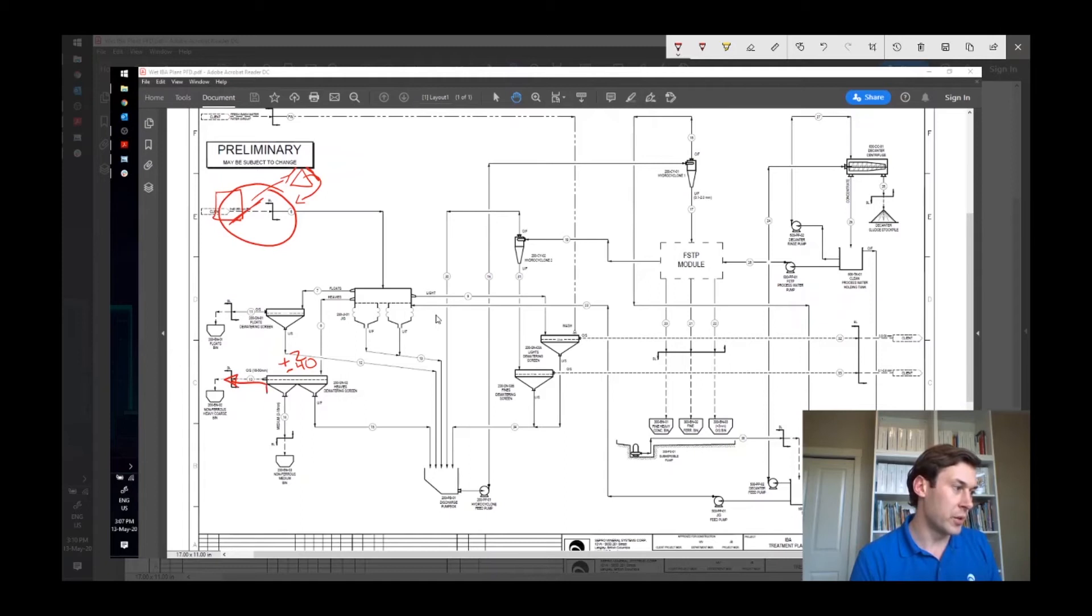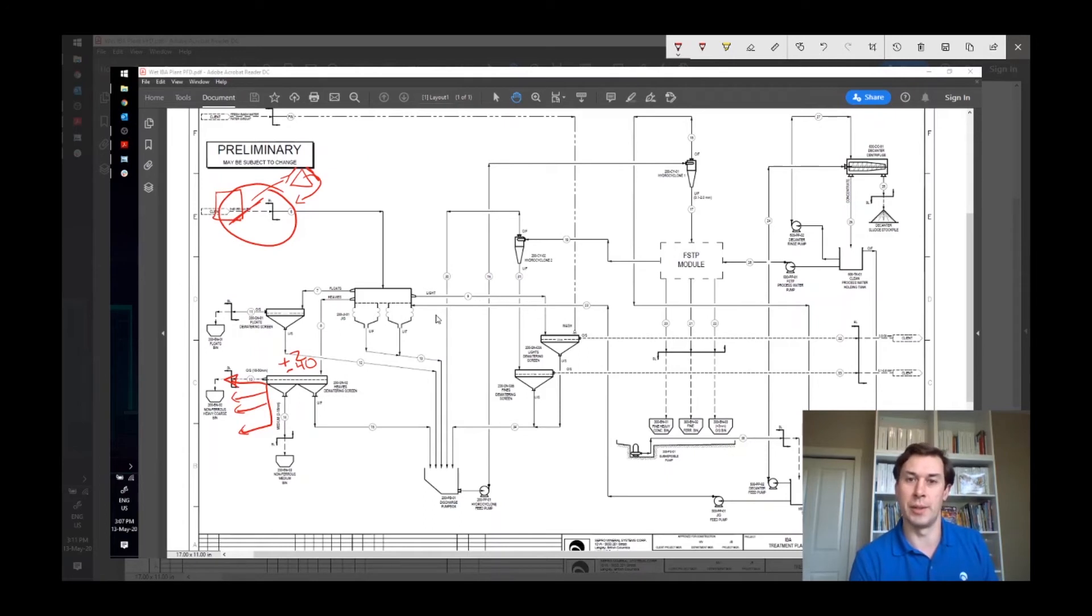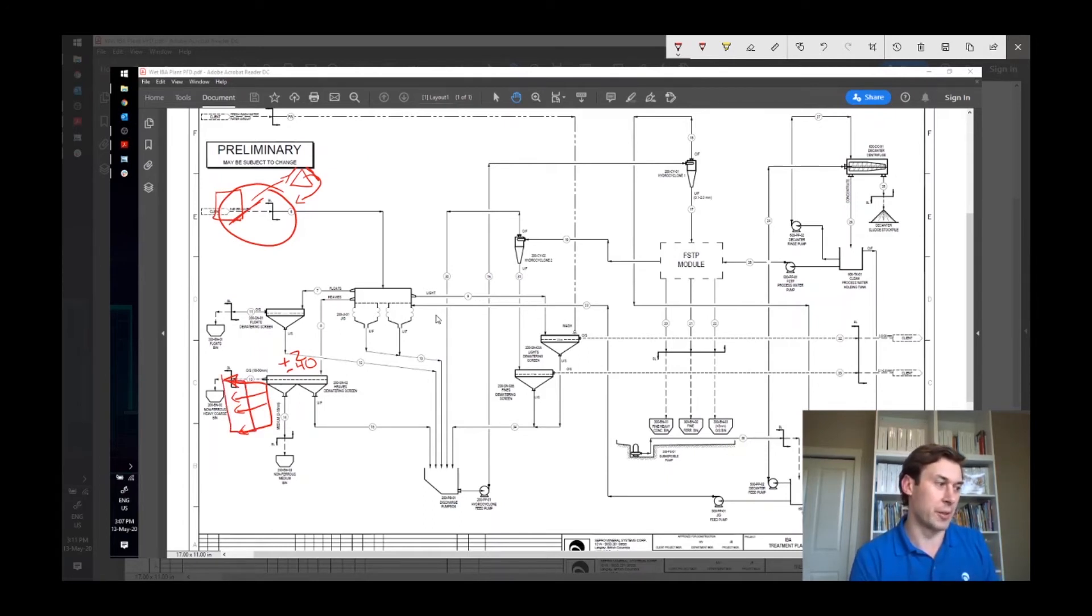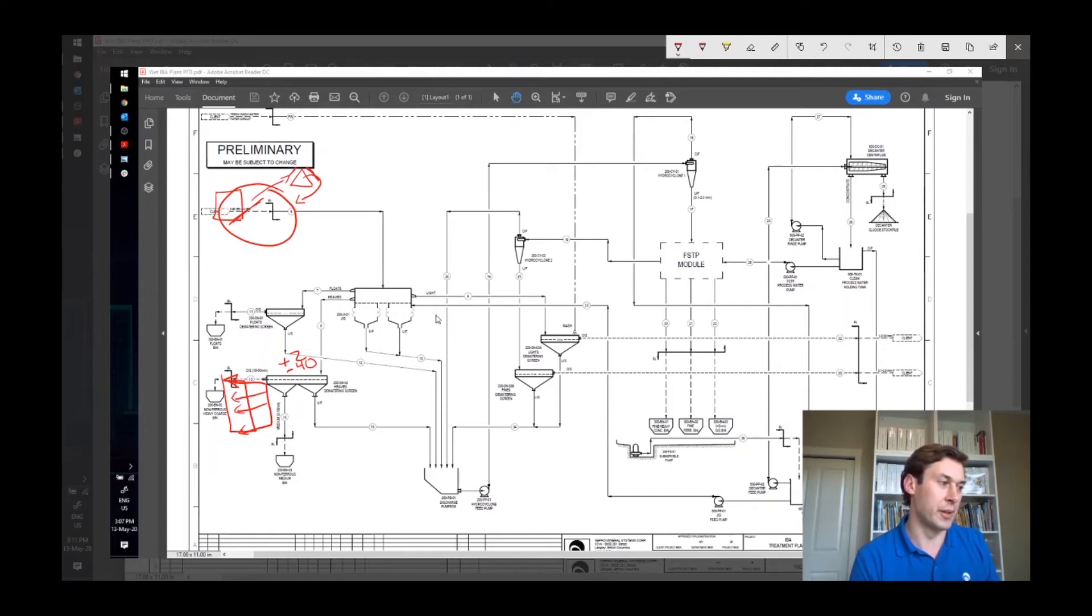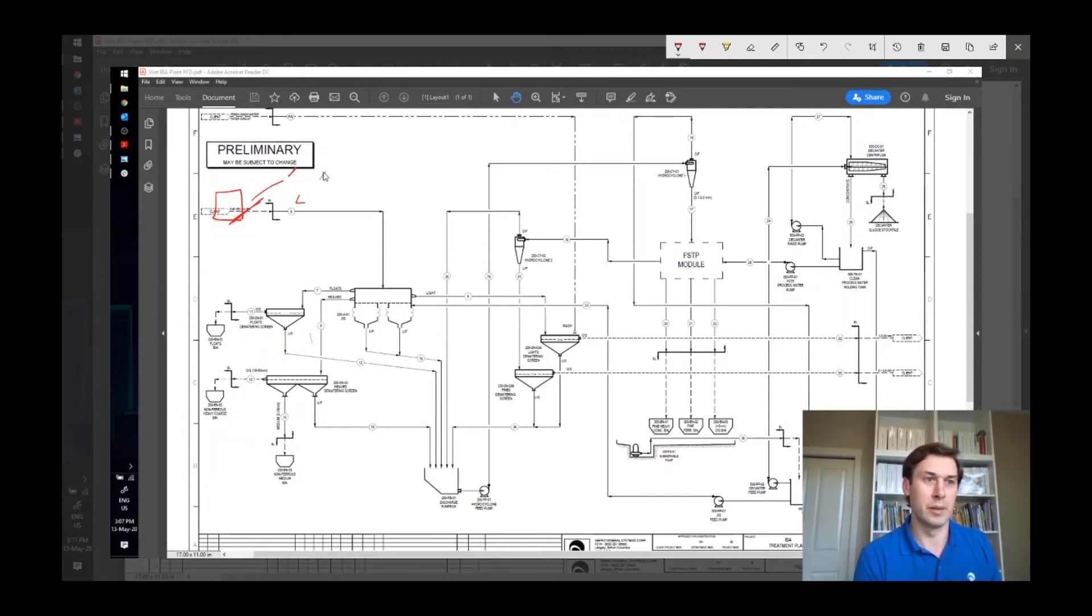And we can do this with whatever size fractions somebody wants. I mean, depending on who the customers are, which smelters you're selling to, what the feed composition is of the IBA. There are a variety of different decisions that can be made on this, splitting it into different size fractions and intensity of eddy current separation, just to make sure we're getting the most out of that product.